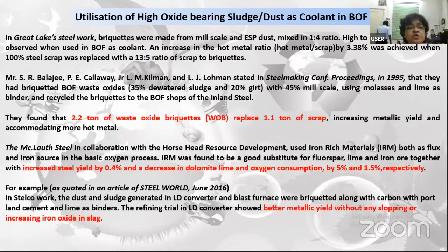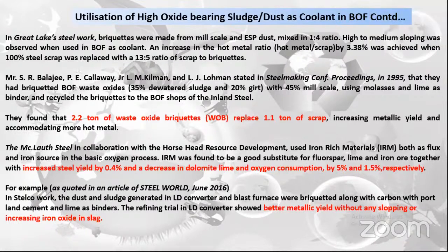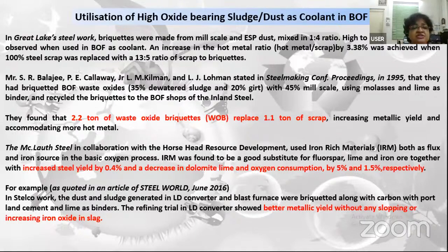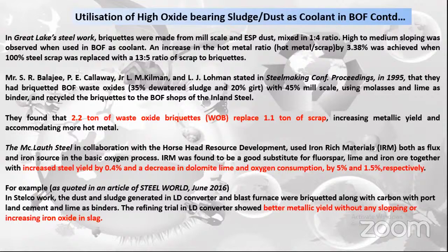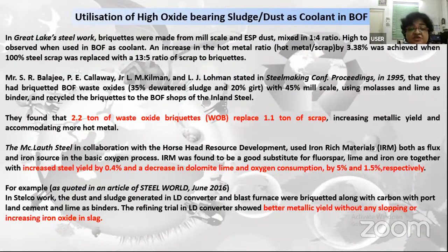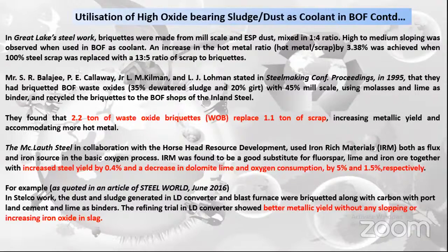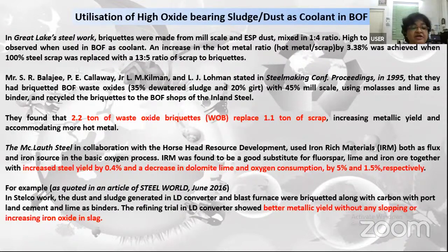Mc.Lauth Steel, in collaboration with the Horse Head Resource Development, used iron-rich materials both as flux and iron source in the basic oxygen process, and IRM was found to be a good substitute for fluorspar, lime, and iron ore, together with increased steel yield by 0.4% and decrease in dolomite, lime, and oxygen consumption by 5% and 1.5% respectively. Similarly, at Stelco, dust and sludge generated in the LD converter and blast furnace were briquetted along with carbon, with Portland cement and lime as binder, and refining trials in the LD converter showed better metallic yield without any slopping or any increase in iron oxide in slag.